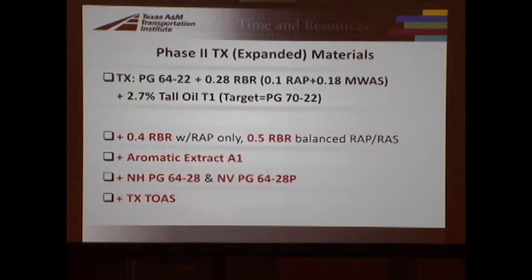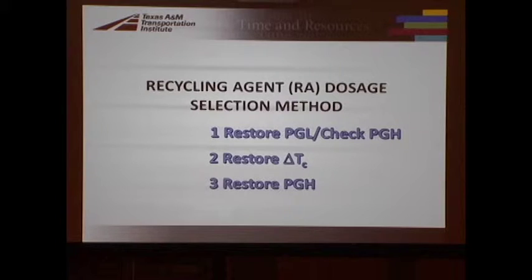We also looked at tear-off asphalt shingles, as those are more prevalent and much more aged than the manufactured and waste shingles. We also wanted to look at a second recycling agent. So we looked at one of the older, more traditional types of recycling agents, an aromatic extract that we call A1. And then we also looked at 2 different binders, a very high quality binder from New Hampshire, which is unmodified, but it's a 64-28, and you're going to see it has a very good positive delta TC value as compared to the PG 64-22 delta TC value. And we also wanted to look at a polymer modified binder. So we looked at a Nevada binder that was used in another field project associated with 9-58. And I mentioned we're looking at TOAS too, tear-off asphalt shingles.